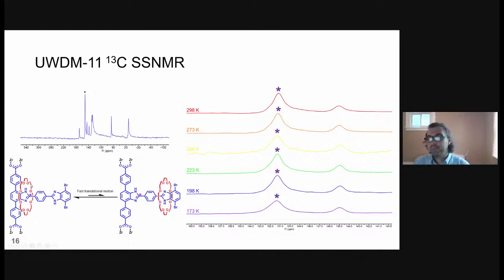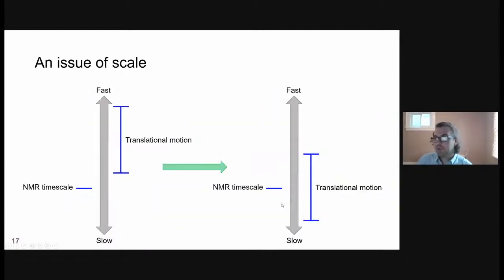So while it's nice to know that when we put the rotaxane in the octahedral cavity we get fast translational motion, we're not able to quantify it in terms of a rate or an energy barrier, as we're not seeing this peak separate out into two distinct peaks at low temperature. So what we have is an issue of scale.